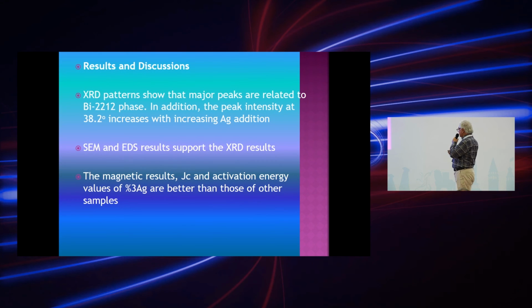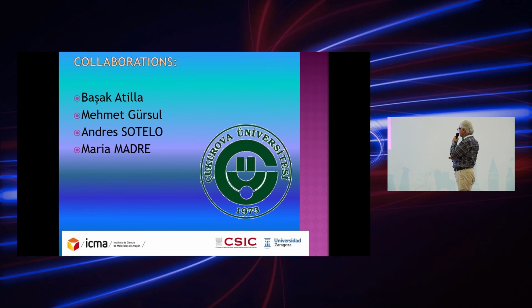Now, I would like to summarize my presentation. The XRD pattern shows the major peaks are related to the 2212 phase. In addition, the peak intensity at 38.2° increases with increasing silver addition. SEM and EDS results support the XRD results. The magnetic results, JC, and activation energy values of 3% of silver are better than those of the other samples. I would like to thank my colleagues Andres Sotelo, Maria Madre, and my PhD students for this good collaboration and for the good results. Thank you very much.